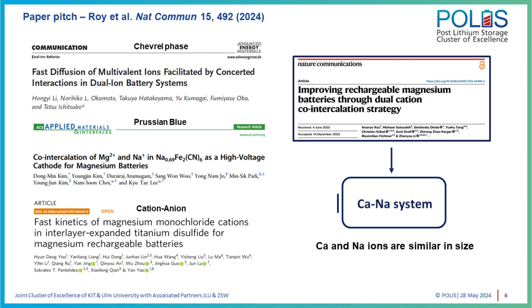The future plan, with regards to my work, relates to a key finding I mentioned: the magnesium and sodium ions didn't work together because of the size differences. So how can we mitigate this and take the next step? Magnesium and sodium are very different in size, but calcium and sodium are very similar in size. So our plan is to try with calcium and sodium in layered materials. Them being similar in size, it's probably a good bet, because then even when the structure changes, both calcium and sodium would prefer the new coordination environments created during a phase transformation.